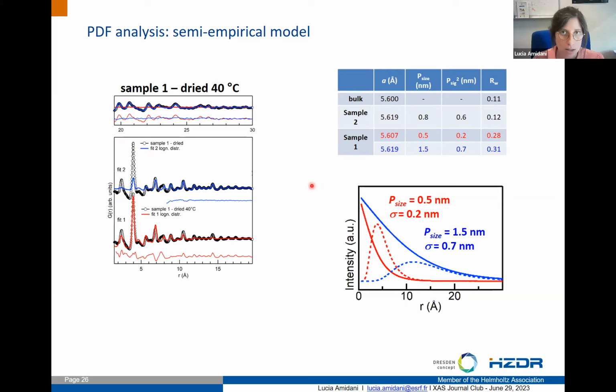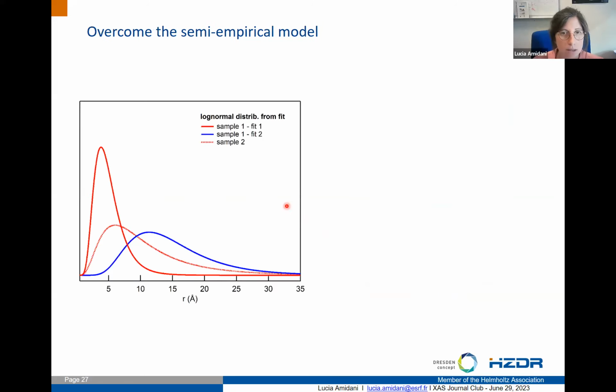So this was a hint that gets us to the point that it's basically a bimodal distribution in this sample. But then another reflection came. So this would be the sort of distribution that I get for my two samples.